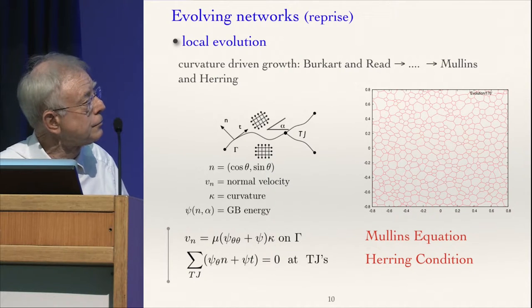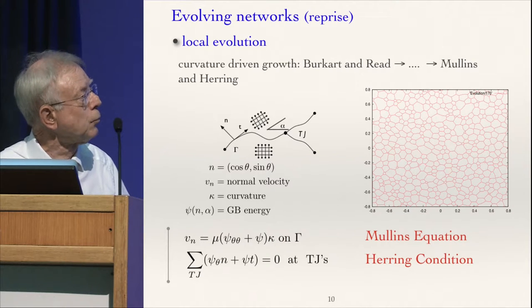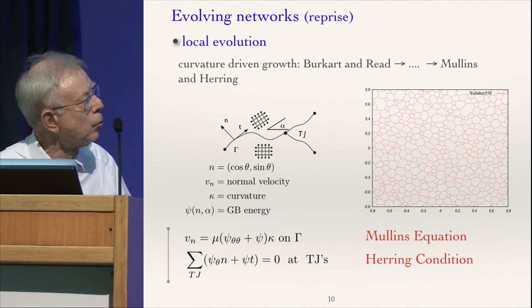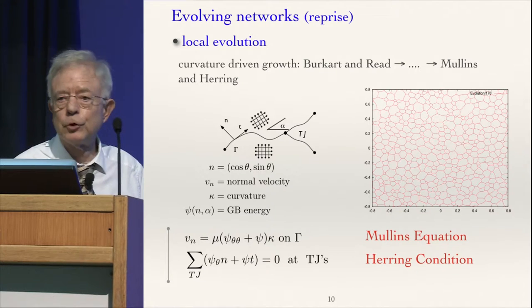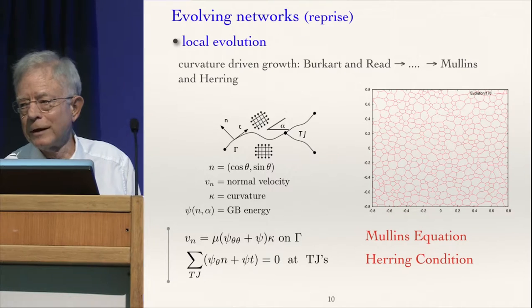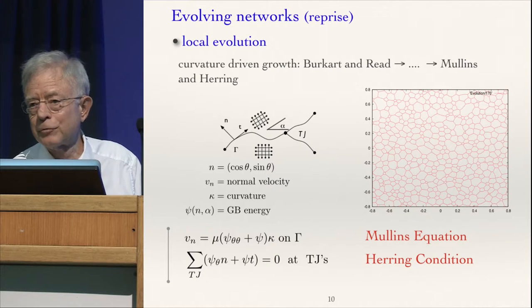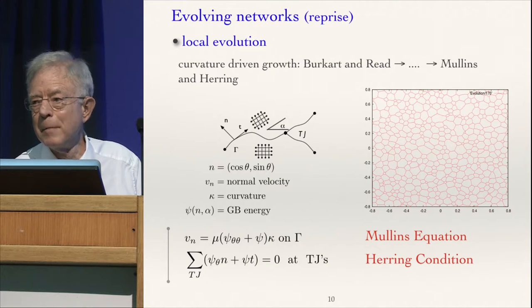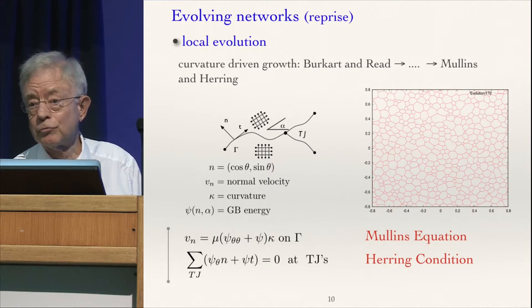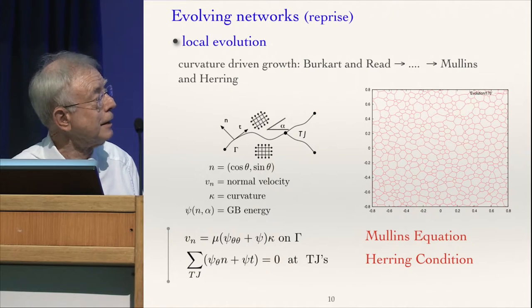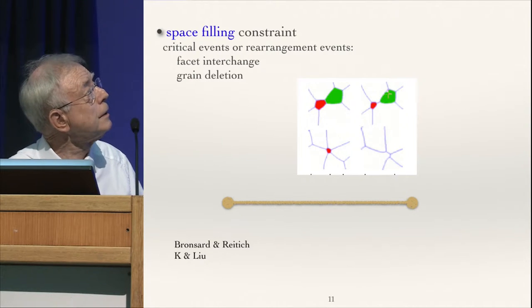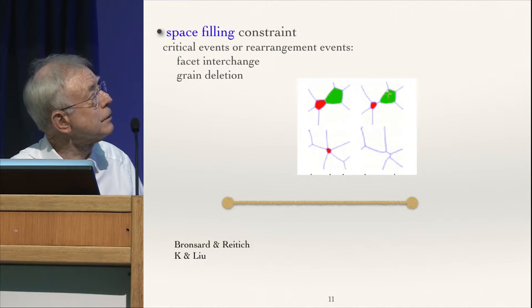And there's a force balance. So this is called Mullins' equation. And there's a force balance at triple junctions, which is called the Herring condition, but it's just the natural boundary condition in equilibrium for this equation. That was actually one of the first things we pointed out to our colleagues, that their force balance condition was just a natural boundary condition. And that meant, of course, that the problem should be well posed, right? Well, they weren't thinking of that necessarily, but we certainly were. And the space-filling constraint means that there can be facet interchange, as you see here, or grains disappear.